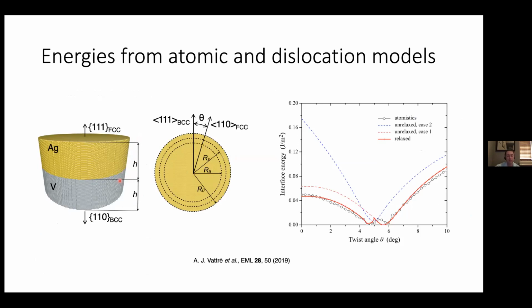So here's an example of a calculation that we did, again, on this silver-vanadium interface, like I showed you on the previous slide. We selected interfaces where the silver facet was the 111 type plane along the interface, and the vanadium facet was a 110 type plane. And we considered various different twist angles. So you can imagine taking this cylindrical model and imposing a relative twist to study different orientations. Then we could calculate the energy of this interface as a function of the twist angle using atomistic models. These open circles that you see here are molecular dynamics simulations that show you the energy of those interfaces as a function of the twist angle.